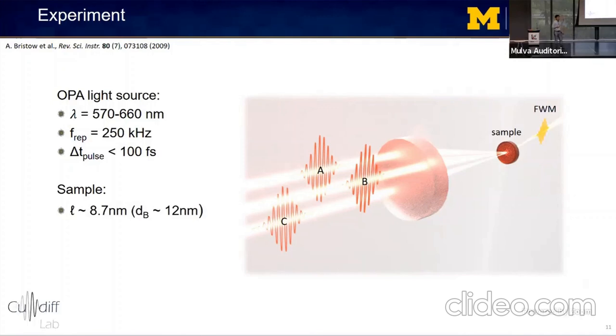And the perovskite nanocubes that we study have an average side length of roughly 8.7 nanometers, which for comparison, the exciton Bohr diameter of bulk cesium lead iodide is 12 nanometers. And to study these nanocrystals at cryogenic temperatures, we suspend them in a liquid called heptamethylnonane, which is a long-branched alkane that forms a transparent glass at temperatures below 100 Kelvin.